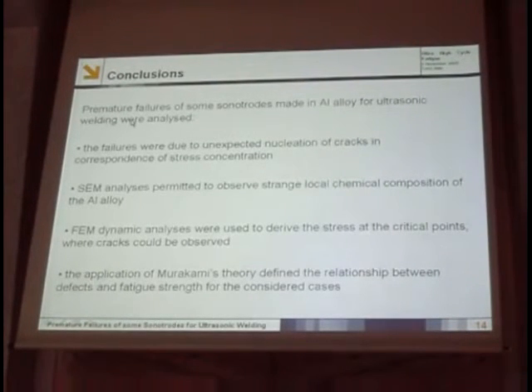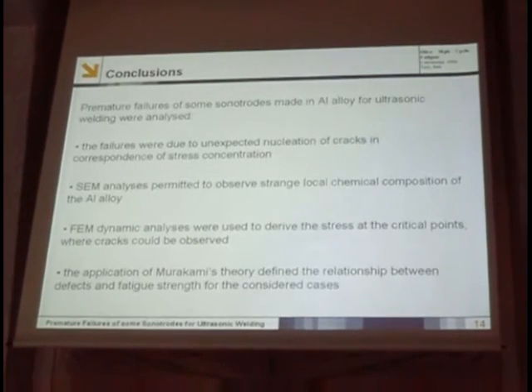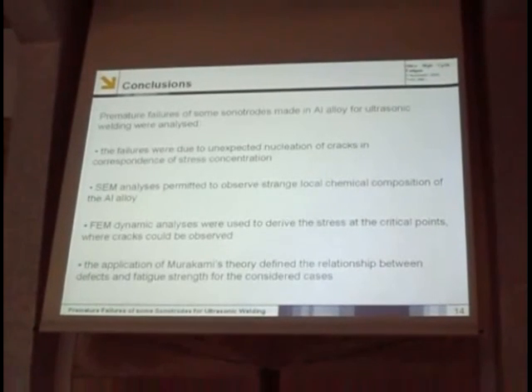Sonotrodes used for ultrasonic welding of plastic objects. So the failures were due to unexpected initiation of cracks in consequence of stress concentration. So observation at the SEM permitted to observe a strange local chemical composition in the aluminum alloy, not expected. So perhaps some error in production of the aluminum alloy. Then FE dynamic analysis and the application of the Murakami's theory permitted to estimate, at least in the first approximation, the influence of defects on the strength of this kind of